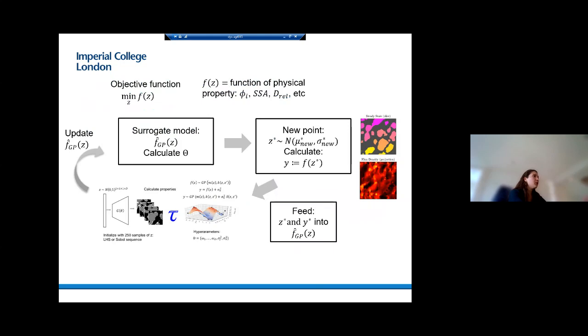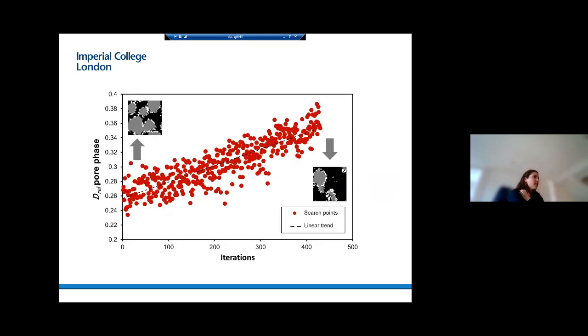Then what we do is that you obtain a set space, and you obtain a surrogate model of that function to be optimized. The Gaussian process would then give you a next point, and you feed that point back into the same Gaussian process, and you update that process until you minimize or maximize the objective function. Some of the properties that we want to maximize, for the purpose of transport properties, are, for example, the relative diffusivity along the pore phase. So this is an example of what's happening. If we start with some values of relative diffusivity that can be pretty low, we can then implement a Gaussian process that can then optimize, moving the set space in order to obtain a higher relative diffusivity.